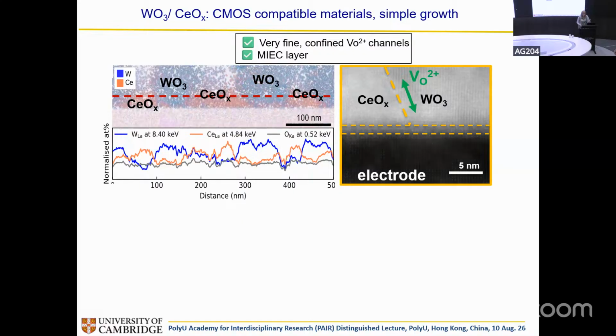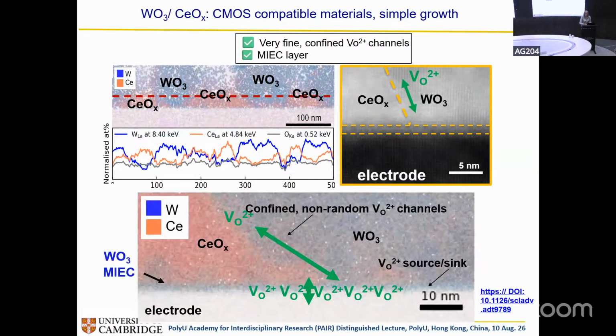But you still have vacancy channels, as we see on the right here. And furthermore, we have this interface region, which you can't see very well in that image, but we show another, much higher magnification image, and we can see that we actually have this thin blue layer above the electrode, and that's all tungsten oxide. What we have here is a tungsten oxide mixed ionic electronic conducting layer, which can act as a reservoir of the channels, the conducting channels.